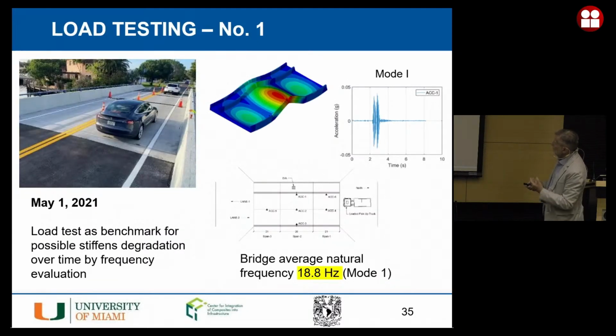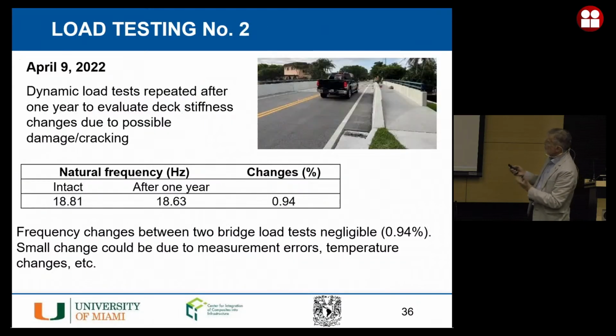What we did immediately after, I'm not going to spend time on this, immediately after construction, on May 1st, 2021, we went out, we did a load test to get a sense of the stiffness of that flat slab. And look at this number. I'm only going to mention the natural frequency of this bridge. And then we went back a year after, and that's what we measure. So instead of 18.81 initial, we are at 18.63. So the change is basically insignificant. We're at 1%. There is no loss of stiffness.